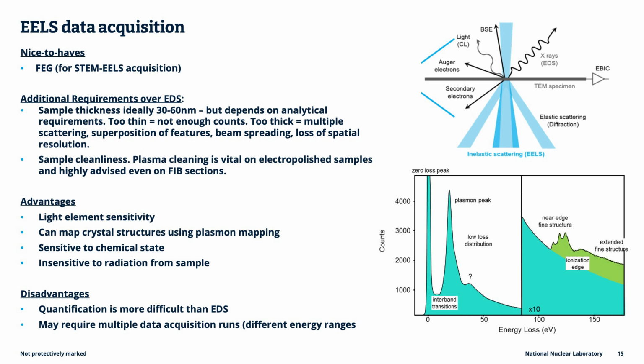One excellent advantage of EELS is that it is insensitive to radiation from the sample. So you can be using an electropolished sample and won't see any degradation because of sample activity. The downsides are that absolute quantification is possible, but it's a lot more difficult than it is with EDS. One of the reasons for that is because, as I said, the intensity of the background regions where these ionization edges occur varies by orders of magnitude amongst the different elements. So the useful edges that you might want to be looking at could be at a much higher energy and will require either a separate acquisition or a much, much longer dwell time to get the statistics up in the spectrum. In EDS, it's a lot simpler.